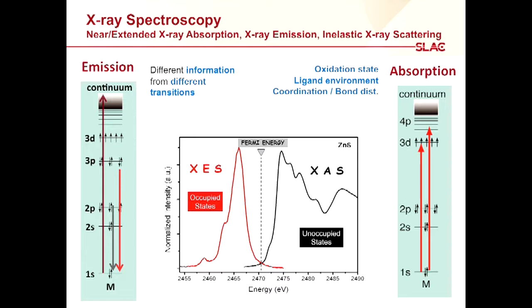And the way we commonly do that, for example, in the unoccupied states, we are coming with some X-ray that has specific energy that can promote a specific electron from a core level to some continuum or discrete state. And when it comes to the occupied states, once we form, let's say, an inner shell vacancy, we simply look at how this relaxation of the atom occurs, and in this way we can probe the occupied states as they are projecting in these vacancies we create.